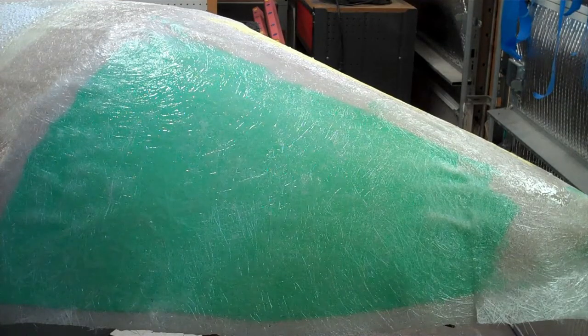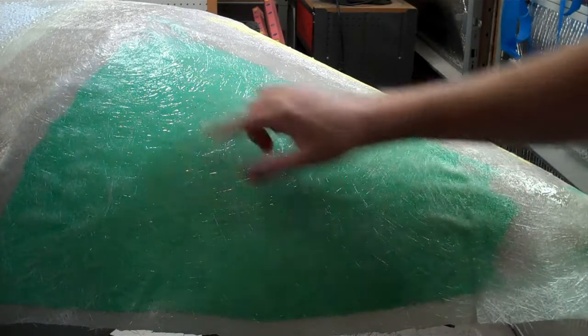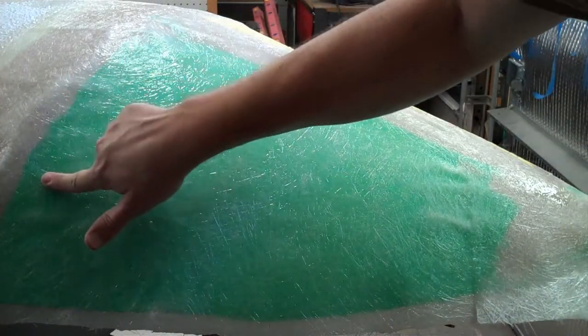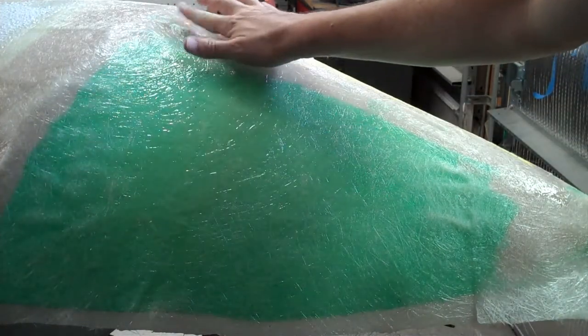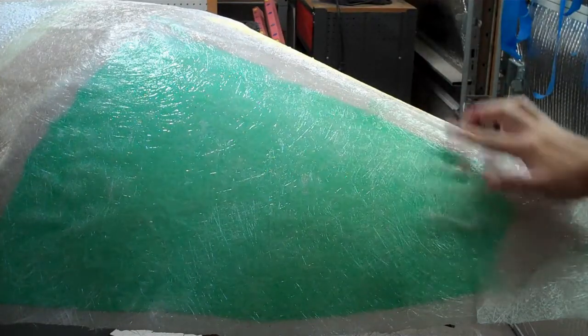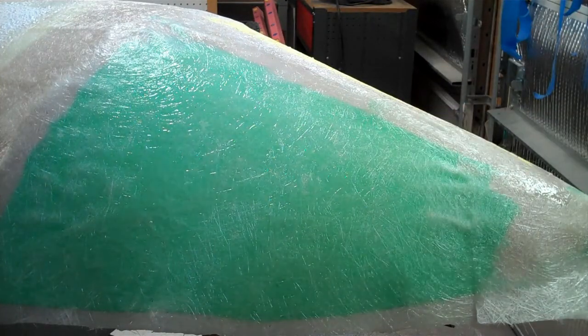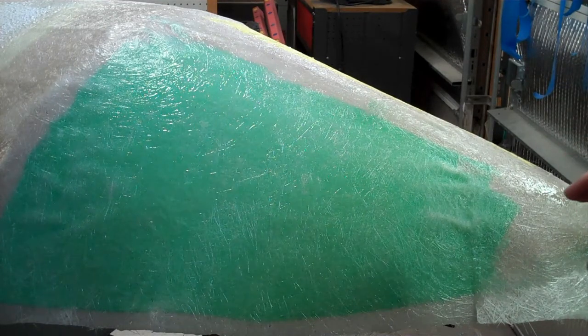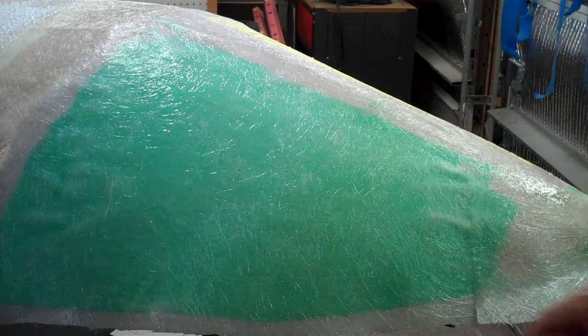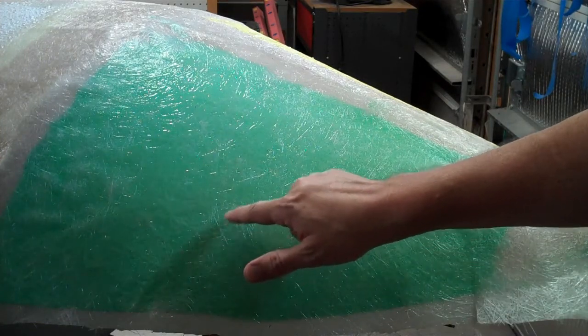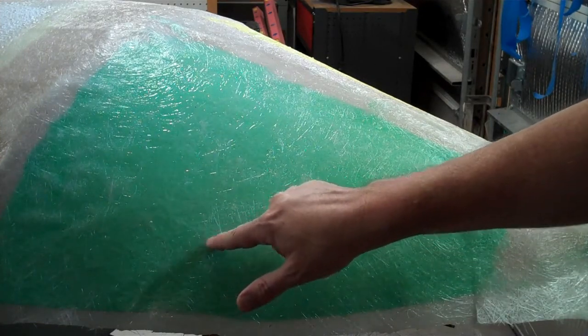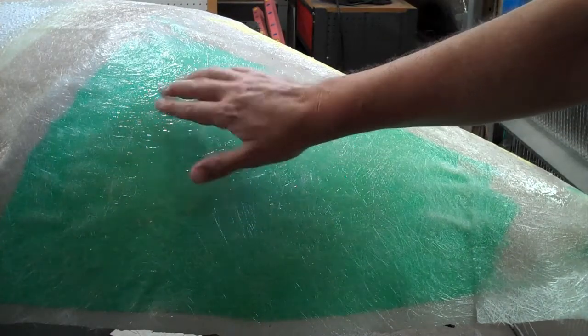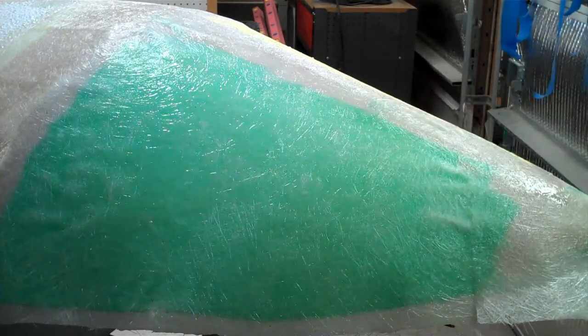Okay, this has dried for 24 hours. You can see there's a couple of places with slight wrinkles, especially in here. That's because I'm using chop strand mat, and the binder doesn't fully release with the epoxy resin. You can see some places where there's visible stranding on the top, and there's other places where there's resin coating that is completely smooth.